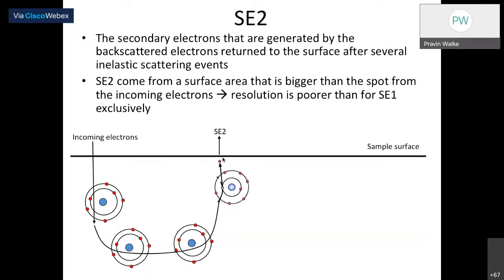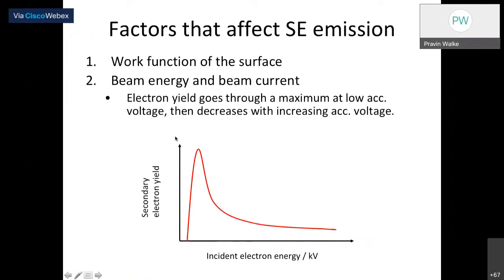So that SE2 comes from a surface area which is bigger than the spot of the incoming electrons, right? And therefore the resolution of secondary electron 2 is quite a bit lower than that of the normal secondary electrons, or primary secondary electrons, right? So what are the important factors which usually affect secondary electron emission? The important factor is the work function of your surface. If the work function is low, it will easily emit, right?